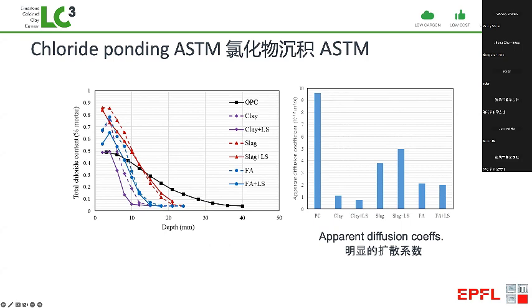But by far the best performance we see with the blend of calcined clay and limestone, which is this solid purple line here. And when we calculate the diffusion coefficient, we can see the diffusion coefficient is 10 times less than for the reference. So we have a 10 times improvement of performance.